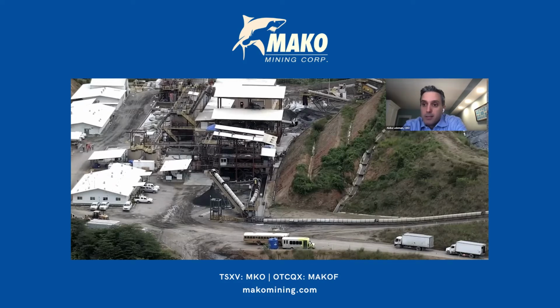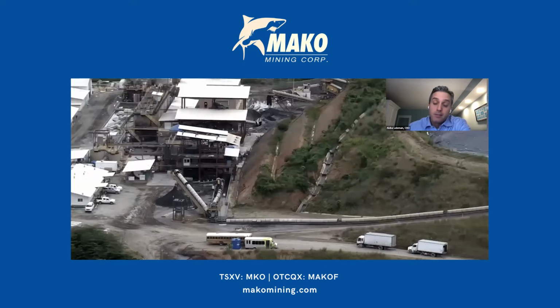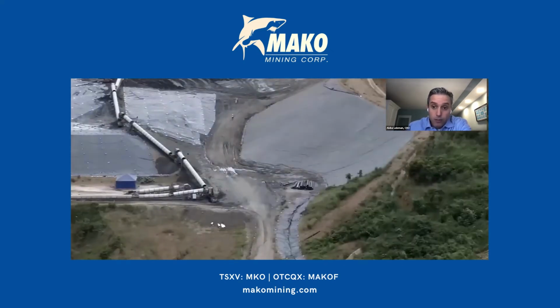I mean, the main difference between a CIL and a CIP is you kind of cycle through all your cyanide in the slurries of your mill before it actually gets to those carbon and leach tanks that you see over to the left, and that has been resolved. And that was actually a very big difference in terms of our experience with the recoveries.